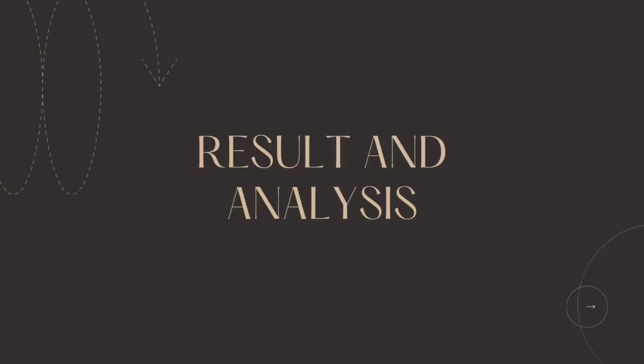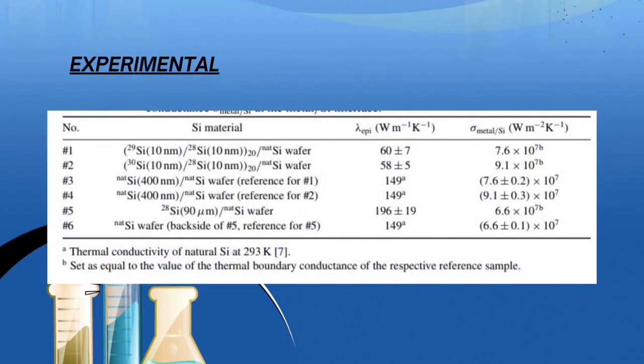Next, the result and analysis. This table summarizes the thermal conductivity and the thermal boundary conductance that were determined from the pump and probe experiments with the isotope and reference samples 1 to 6. Within the experimental accuracy, this supports the enhancement of about 10% reported in the literature for the thermal conductivity of pure 28 silicon compared to natural silicon.